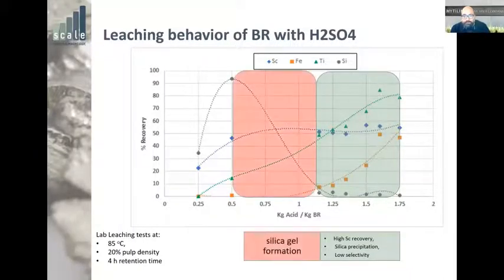This middle region, you see we don't have any markings in there. It's because in this region we form silica gel. So in this region we dissolve all the silica in the bauxite residue and don't have enough acidity to drive it to reprecipitate. So this region is basically a region we cannot use.